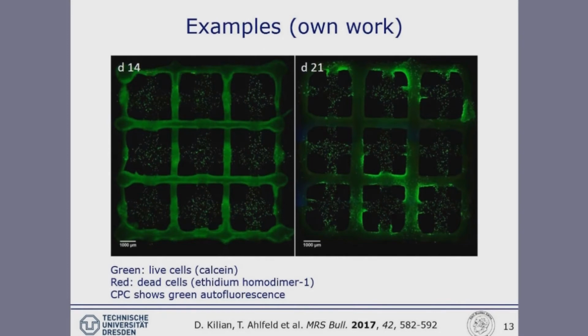Looking at later time points, 2 weeks and 3 weeks after printing, these are our live/dead stainings. You can nicely see that we still have mostly live cells here in our hydrogels. We still have completely open macropores between the cement strands, so the hydroxyapatite strands, and our hydrogel. And astonishingly, we observed that after 3 weeks of culture, first cells have started to migrate out of the alginate-based hydrogel onto the surface of the stiff calcium phosphate cement strands, because human mesenchymal stem cells need to adhere using integrins to something they can bind to. They don't have, of course, integrins to bind to the algae-derived polysaccharide alginate, and therefore some of the cells seem to prefer to stick to the calcium phosphate surface, which provides a maybe more natural surface to these cells, especially, of course, if we drive them towards the osteogenic lineage.